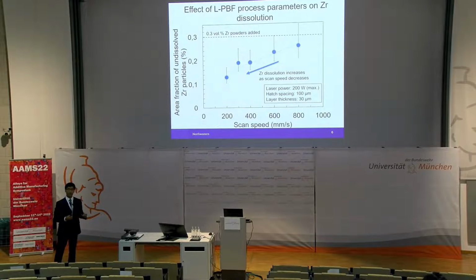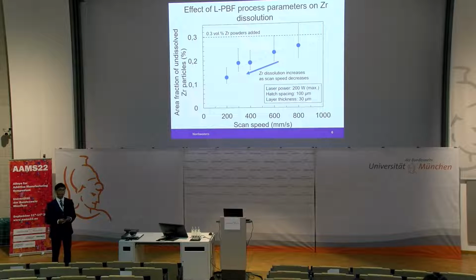So the goal now is to vary the laser powder bed fusion process parameters and see if we can achieve a more homogeneous microstructure. The first parameter that I'm going to talk about is the effective scan speed. Here we keep the laser power, hatch spacing, and layer thickness constant. I'll also note that laser power is the maximum power that we can achieve on the machine. We then measure the area fraction of undissolved zirconium particles by image analysis techniques.